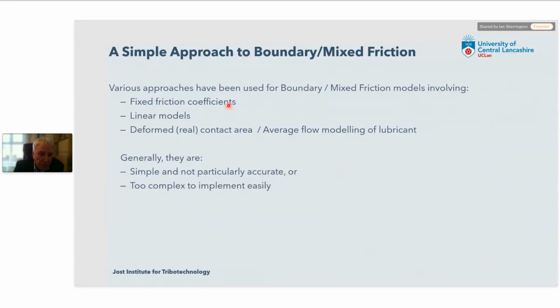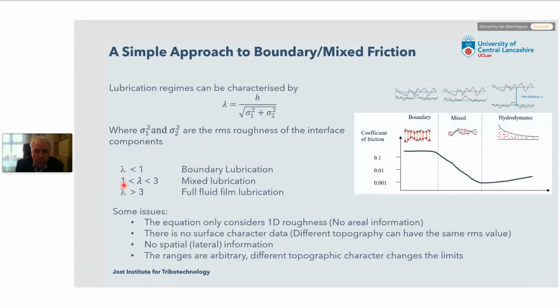So as I've said, friction coefficients can be modeled. We might use linear models, or we might use quite complex models that involve predicting the deformed real contact area using various kinds of surface contact models, so Williamson, Greenwood-Tripp for example, and average flow modeling to get flow coefficients for the lubricants. So they're either simple in the case of linear models, or complex and not easily implemented. And what we wanted to try and do is to put together a model that, if you can calculate the lubricating film thickness in a contact, then you could very quickly, perhaps in an hour, build a little spreadsheet or something to predict the boundary and friction power losses that go along with that. So this is how we went about that.